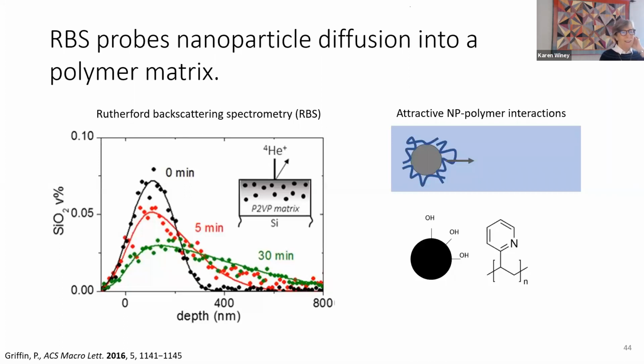And we wait longer. So now we're using Rutherford backscattering. It's the same ion beam, but we look at a different signal coming off: helium in, and then we look at the helium come off, and it can give us a concentration profile now of the silica rather than the deuterium as a function of depth. Okay, so at time 0, we just have the nanocomposite at the top. This is not drawn to scale. The matrix is much, much thicker. And over time, we can watch the diffusion of the particles in. Again, one fitting parameter for the diffusion coefficient of the particles.